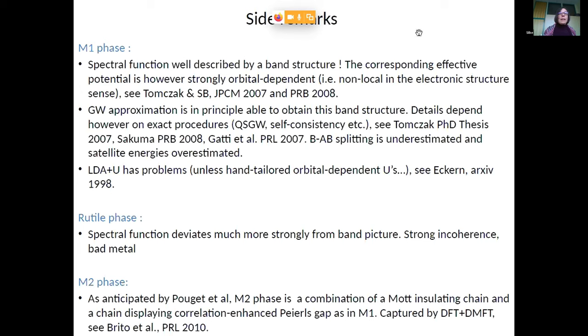One can then check if this effective band structure is also possible to obtain from other methods. So there are a few very interesting GW works. I can comment more on this if there is interest. LDA plus U has some problems. And I think overall, you should really think of this M1 phase as a dimer phase in the sense of the Hubbard dimers. In the rutile phase, the spectral function has much more deviations from just the pure band picture,